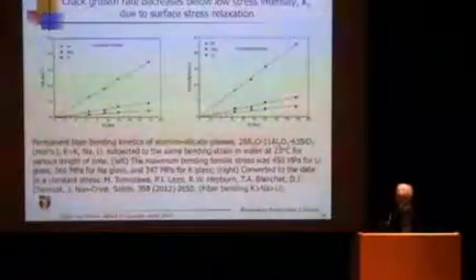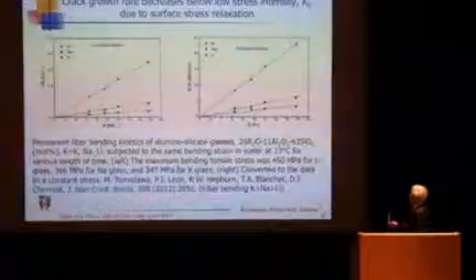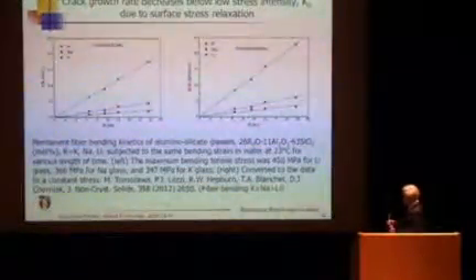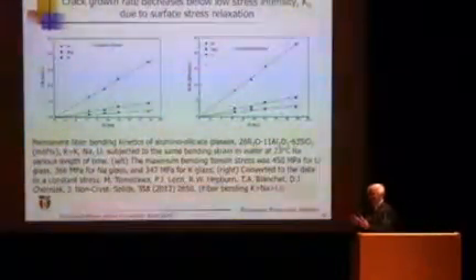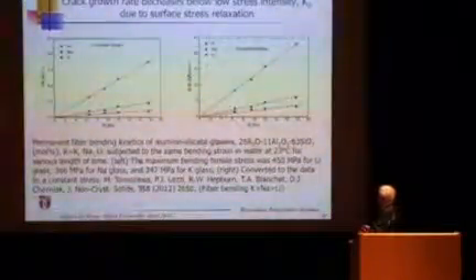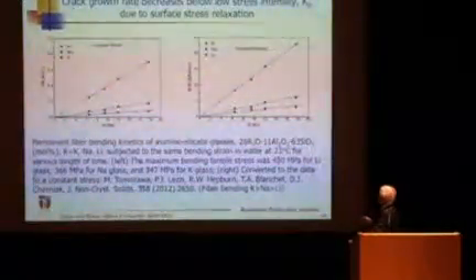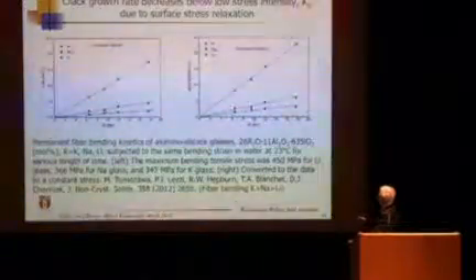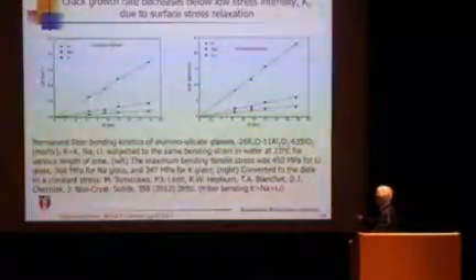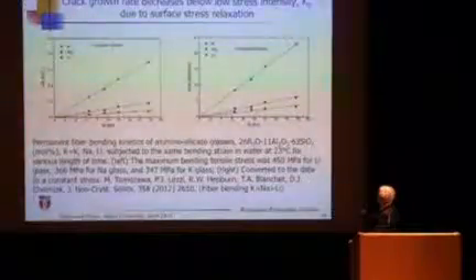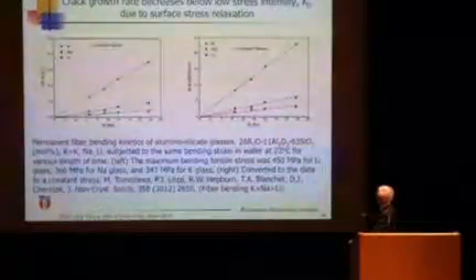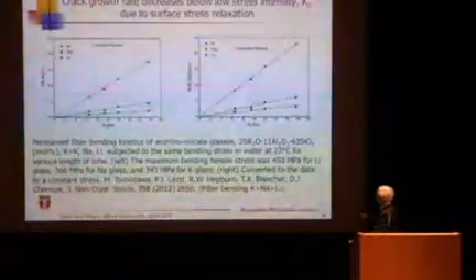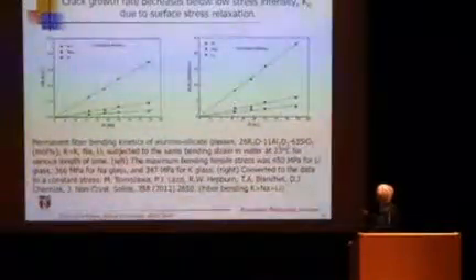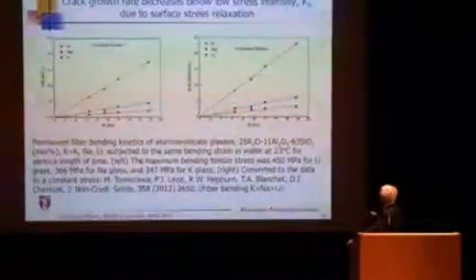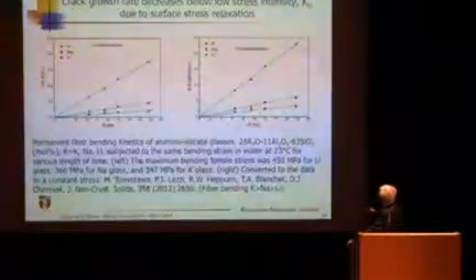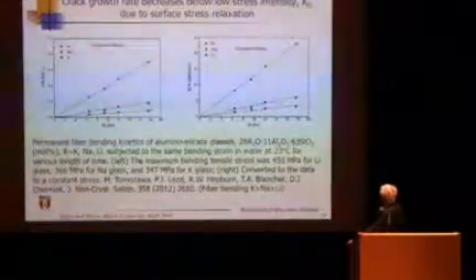So we took those three glasses, potassium, sodium, lithium, and we bent and measured bending kinetics, how quickly we bend. This potassium glass has a small radius of curvature, meaning it bends faster. And sodium is next, and lithium was least. They have different modulus values, so we normalize to constant modulus by multiplying by the modulus, and the trend is still consistent.